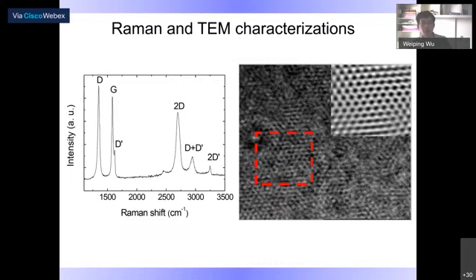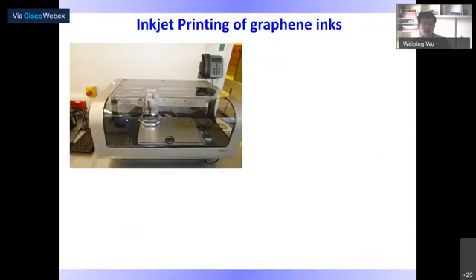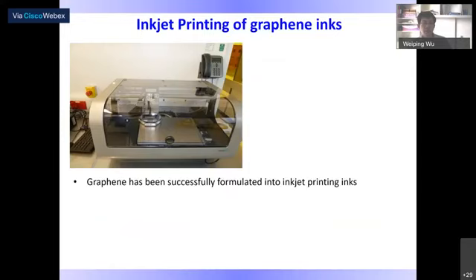Using this process, graphene can be produced at a very low cost but in high quality. This graphene lattice, unlike GO, contains nearly zero defects, and through Raman we can see that the D peak, even though it is there, comes from the edges of the graphene. It's not structural defects. Therefore, using this ink, I inkjet printed on the substrate and got this thin film for device application.